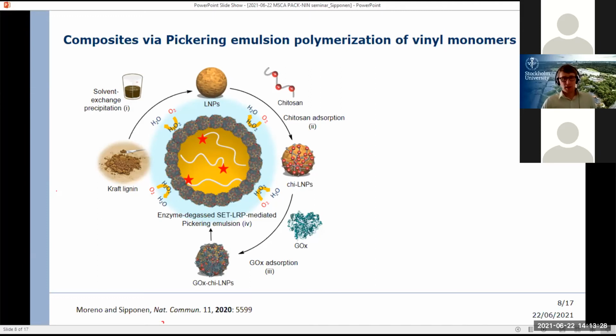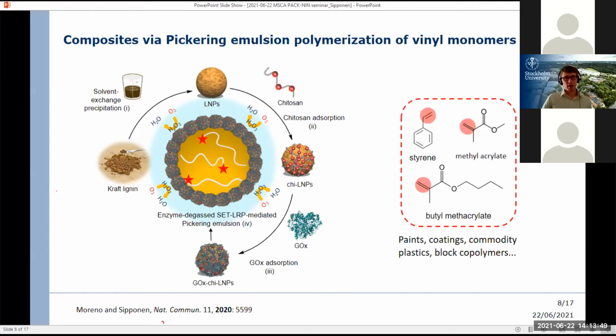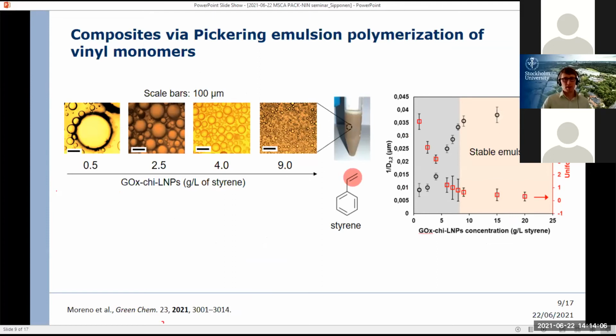Coming to this slide, I want to just present how we managed to produce polystyrene-lignin particle composites. I don't go into details, but the idea was that we made an in situ polymerization using an emulsion polymerization system. And these emulsions were stabilized by the lignin particles that were coated with enzymes. This enabled us to use different non-water soluble hydrophobic monomers for the polymerization. And basically, this combined the best of the two worlds. The lignin particles were very good for the emulsion stabilization, but also then they formed very nice polymers